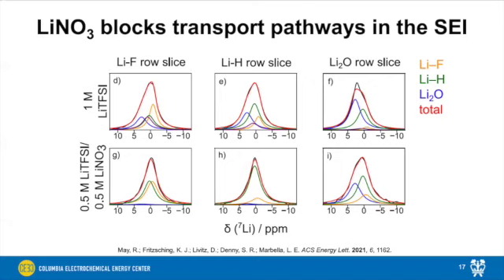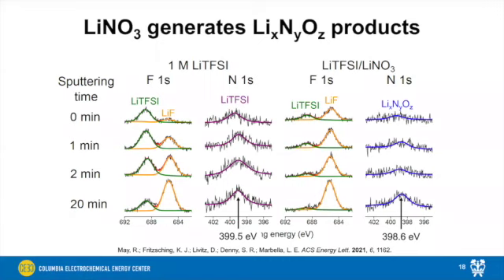The only thing different about this sample is that we've added in this lithium nitrate. So what we think is happening, or what we hypothesized at the time, was that this nitrate was being preferentially reduced on top of the native oxide and blocking this exchange event. In order to figure out what was happening, we didn't feel as though we had good enough resolution in our lithium 7 NMR to actually interrogate this. So we performed some depth profiling in the XPS to see if this is what was actually happening.